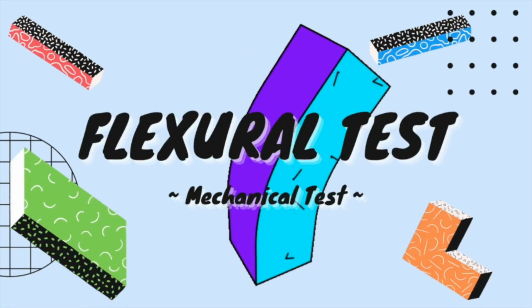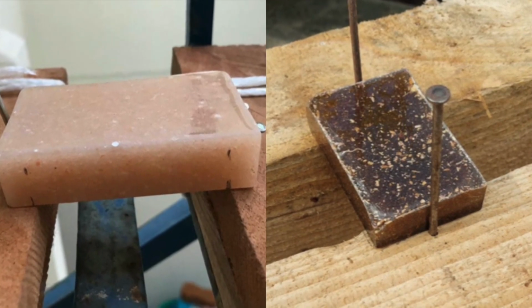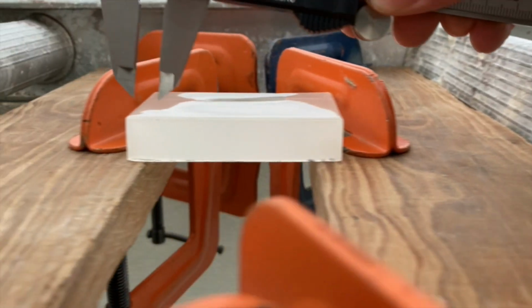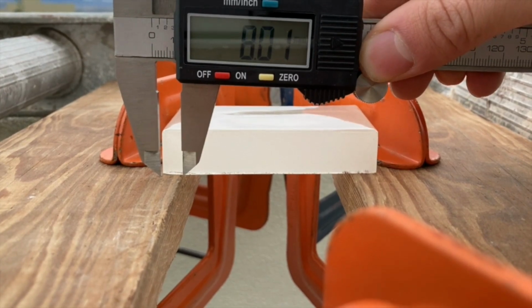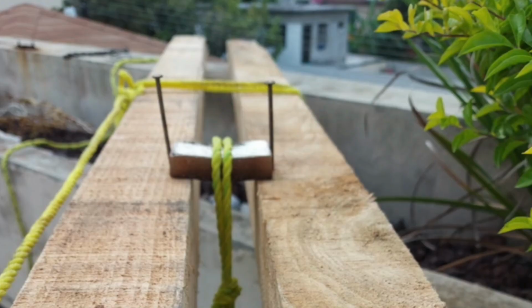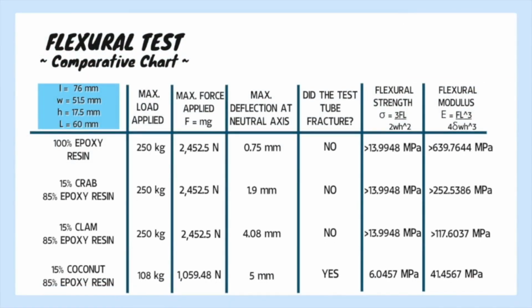Flexural test. The test tube was placed on a wooden support, leaving a distance of 8 millimeters between each end and the supporting points. A rope was tied to the sample and placed at the center of it. All the loads were measured with a scale. During the test, the loads were gradually applied until the sample tube was fractured or the limit of 250 kilograms was reached. According to the flexural modulus and deflection obtained, it is possible to conclude that the pure epoxy resin was the one which opposed more to deflection. The second best material was the crab composite, and the worst was the coconut.